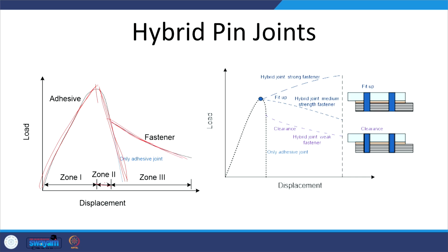So, this is the joint in zone 2, where after the failure a little bit of slipping takes place, and then the mechanical fastener starts taking the load. Okay, so this blue line corresponds to the only adhesive joint, and then the mechanical fastener comes into the picture. The load displacement curve of zone 3 primarily corresponds to the mechanical fastener.